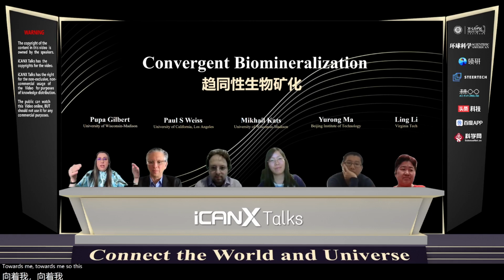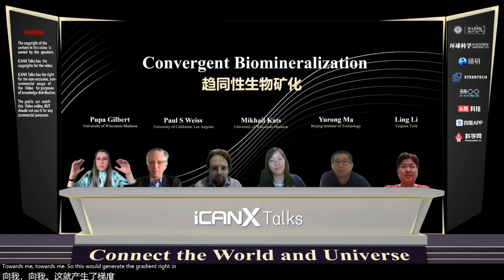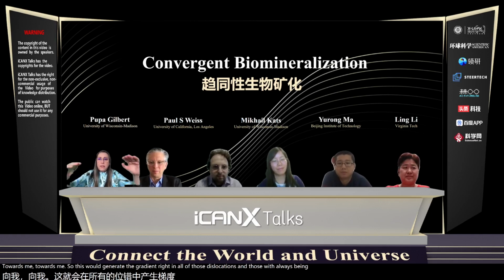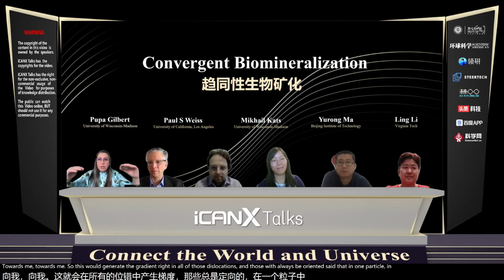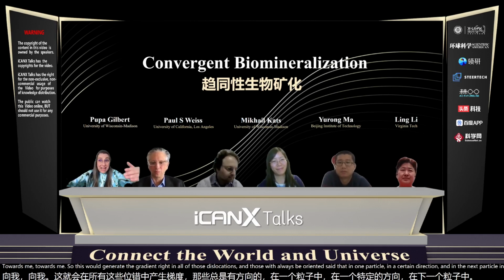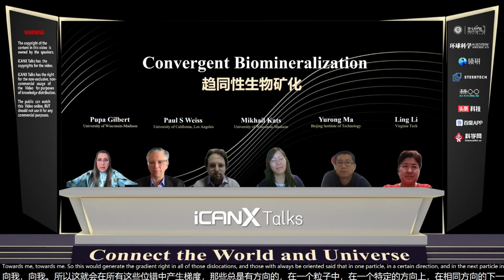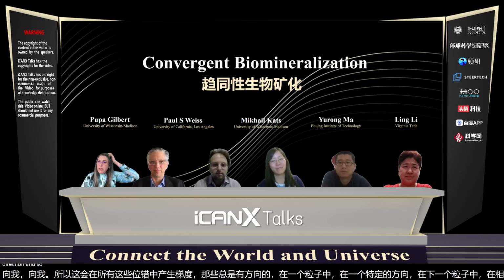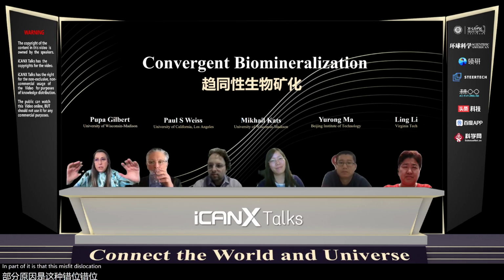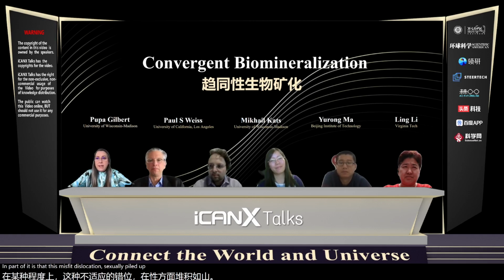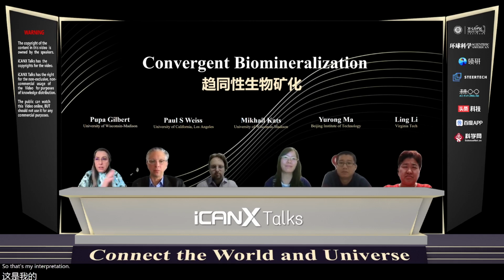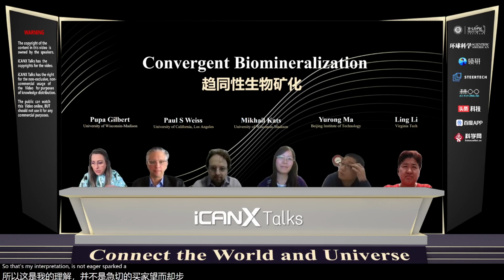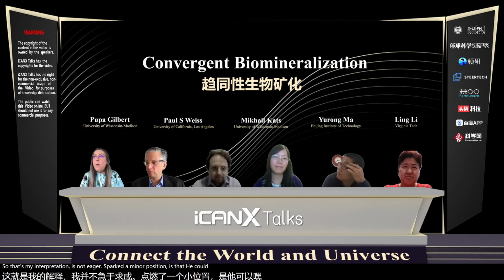So this would generate a gradient in all of those dislocations, and those would always be oriented in one particle in a certain direction, and in the next particle in the same direction, and then in the same direction, the same direction. And so part of it is that the crystallinity propagates from one to the other, and part of it is that these misfit dislocations actually pile up, and that's what generates the gradient.